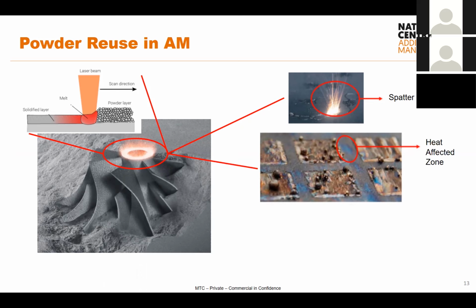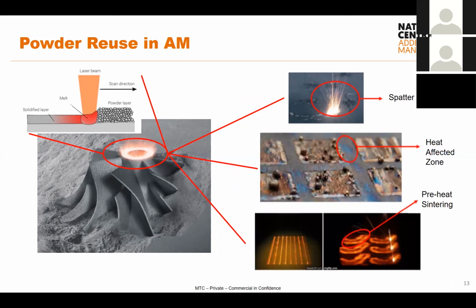Now, the third one, and if you're not familiar with electron beam melting as a technique, you won't have come across this, is preheat sintering. In electron beam melting, for all sorts of reasons, we have to pre-sinter the material in order to avoid something called the smoke, effectively where you build charge up in your particles and they basically repel one another and you get a big puff of smoke, of powder particles flying up into the air.